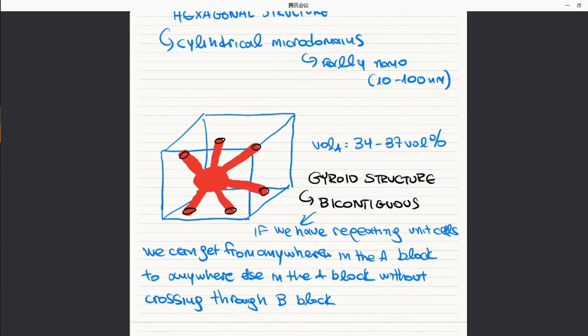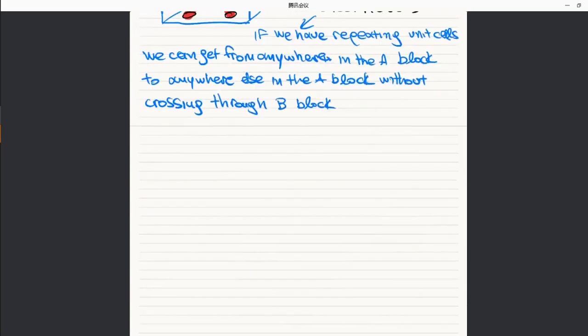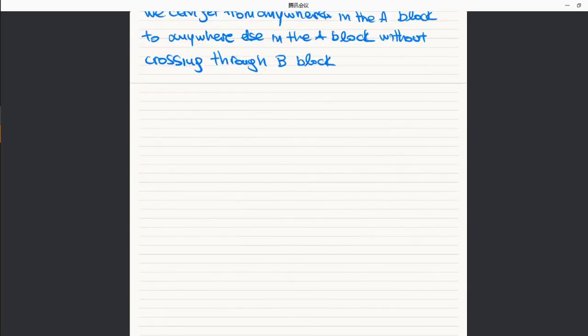Okay, this takes place at very narrow volumes though. Notice that it's only 34 to 37% volume percentages in order to achieve this gyroidal structure. Okay, I notice that we're overrunning a bit, so I'll finish with the final morphology and then we'll take a break. So the final morphology ranges from the volume of A block being in the range of, let's say, 38 to 50 volume percent. And in this case, we have a lamellar morphology.